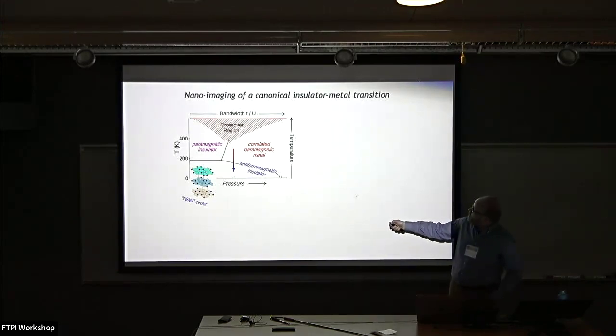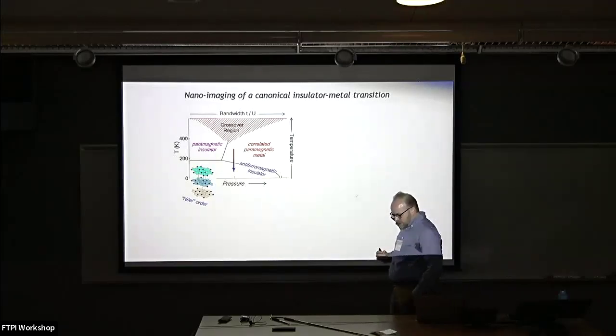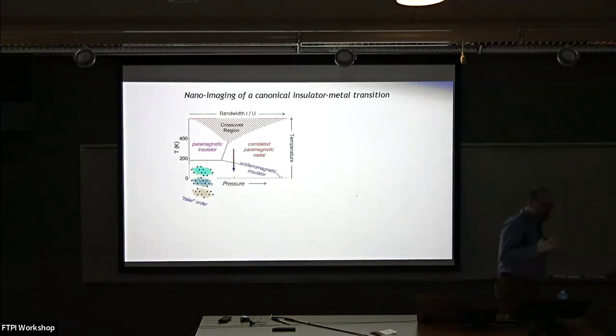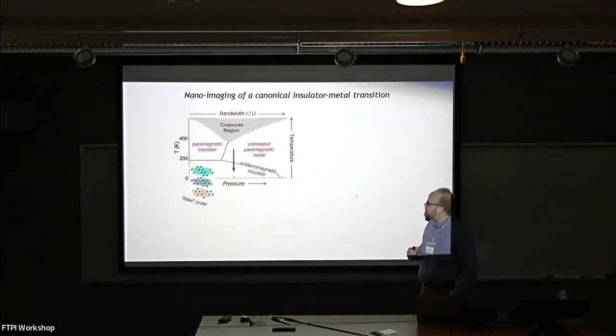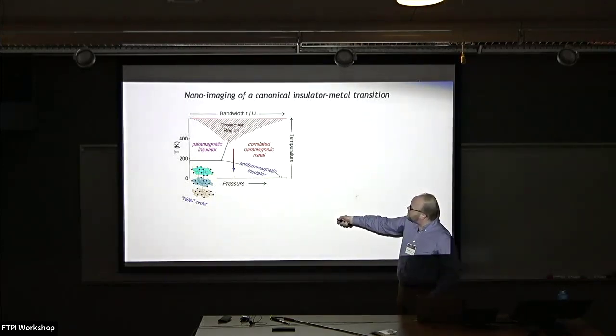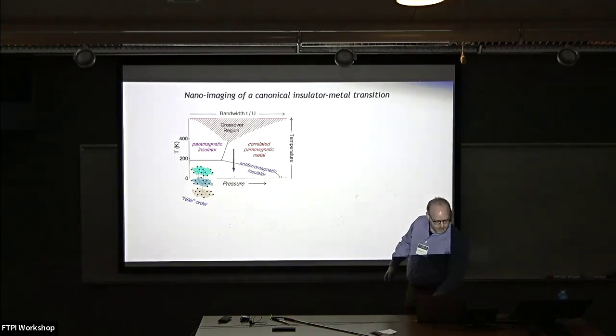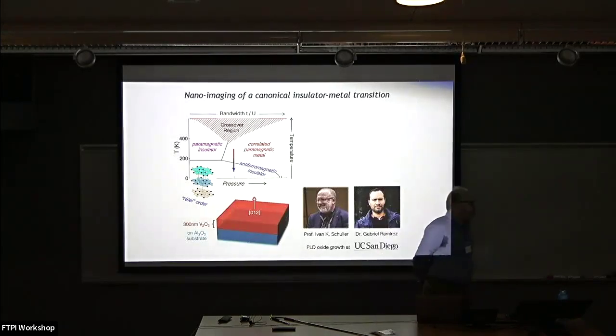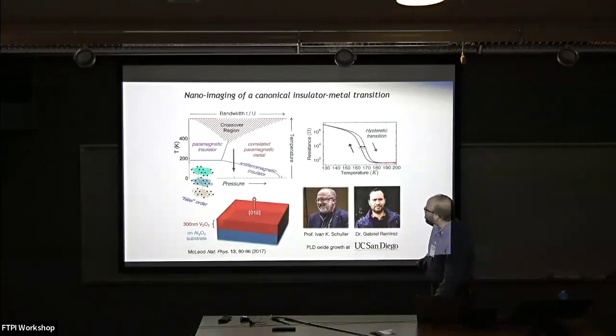I'll also point out about this fun material, which was originally classified as the canonical Mott insulator by virtue of its phase diagram. As often is the case, the material turned out to be a little bit more complicated than just the canonical Mott insulator picture. But nevertheless, all of the features in the cartoon phase diagram are emulated here. So for the data that I'm going to show you right now, I have to give credit to sample providers. The king of vanadium oxides, Ivan Schuller, provided the thin films grown on sapphire that we imaged using this nano-optical technique through this phase transition.